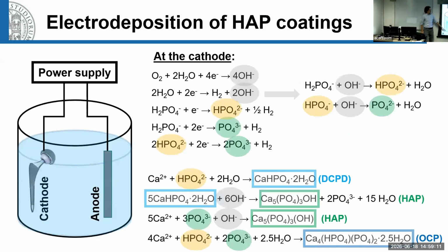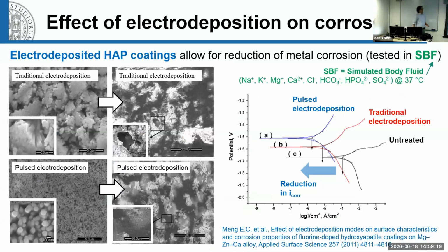So by forming hydroxyapatite layers on the surface of the metallic implant, it's possible to reduce its corrosion. Here in this graph, you can see a comparison between an untreated metallic implant and the same metallic implant with some coatings formed by electrodeposition on top. So there's a shift in this direction in this graph where you have the potential and the current. So it means that there is less current circulating in the system, so decreasing corrosion.